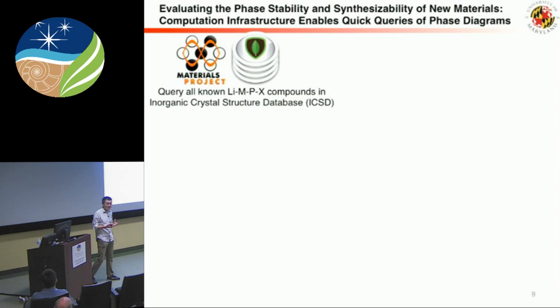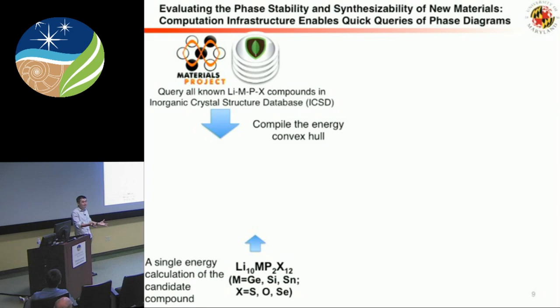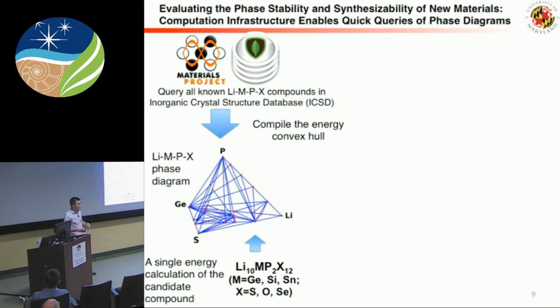So what we did first was to see whether this material can be made, whether it's a really stable phase. And we can really do that computationally, based on the materials database enabled by the Materials Genome Initiative. Essentially we get all the compounds in this system, and each of them has a calculated energy. Then we compile the convex hull and we can get the phase diagram.